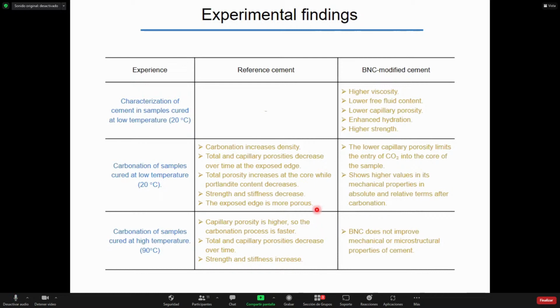When we modify the curing conditions and cure it at 90 degrees, for all samples we saw that capillary porosity is higher, so the carbonation process is faster. Total porosity decreases over time and the strength and stiffness increase as well. In this case, the bacterial nanocellulose does not improve any mechanical or microstructural properties of cement.